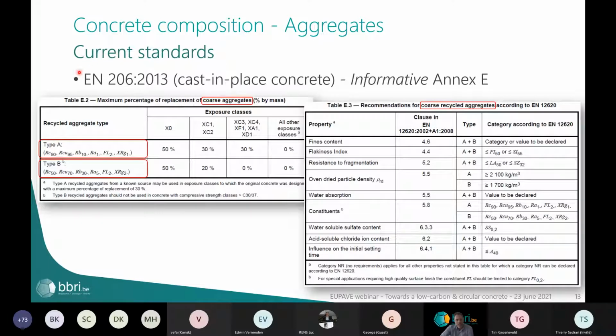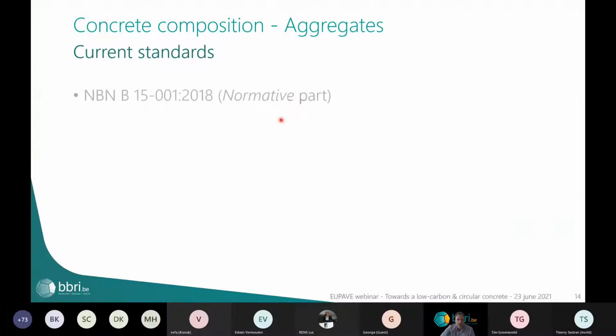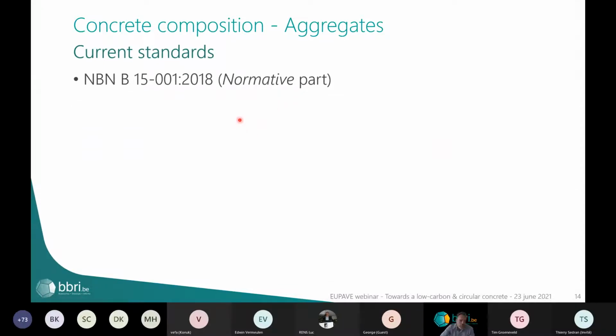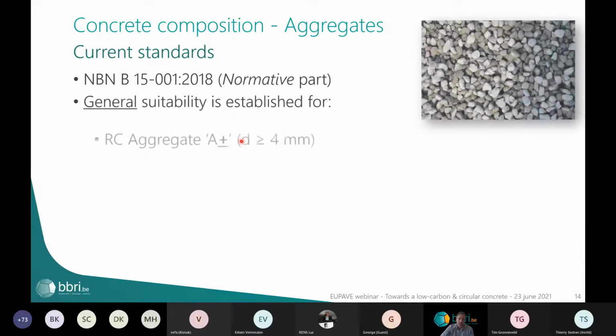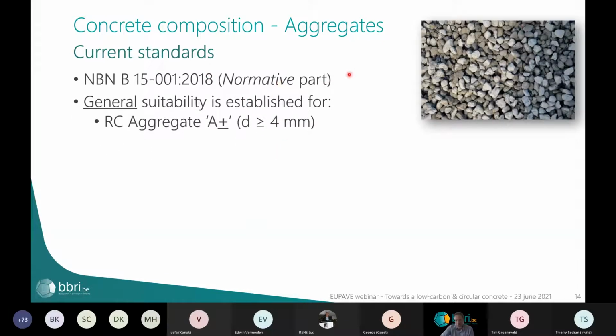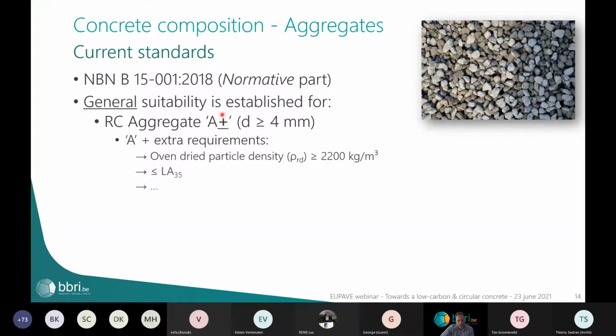The standards don't speak about the fine aggregates, the sand in the concrete. Now, I can only speak for Belgium, of course, because for other countries I'm not specialized. But the Belgian standards since 2018, in the normative part of the standard, so it's not an informative or recommendation, it's very normative, say that the general suitability is established for the recycled concrete aggregates. You can see here a plus compared to the European standard. It only spoke about A.